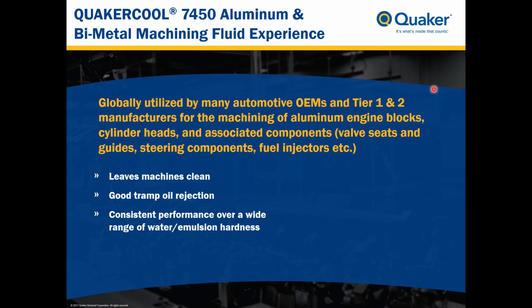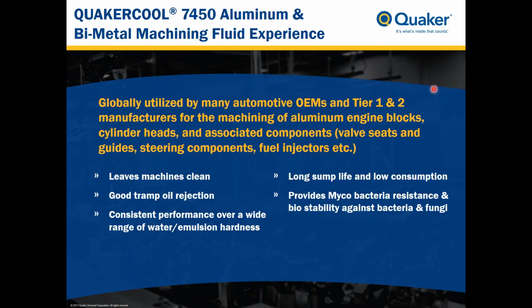Some of the behavioral features of this fluid: it's a very clean operating fluid. It is a semi-synthetic fluid, a very tight emulsion, wets out well and leaves the machine very clean during operation. It has good tramp oil rejecting properties. It's very compatible with increasing water hardness, giving very consistent performance and stability over a relatively wide range of water hardnesses in the emulsion. Being a tighter emulsion, it is stable to some of the influences of contamination and changes. It provides a very good sump life in its operation with low consumption.